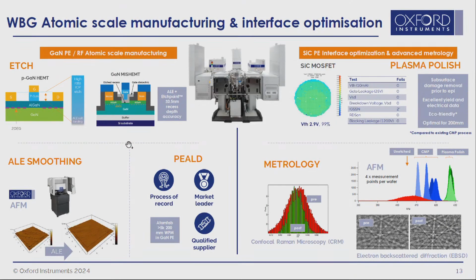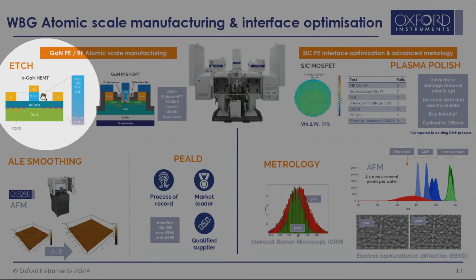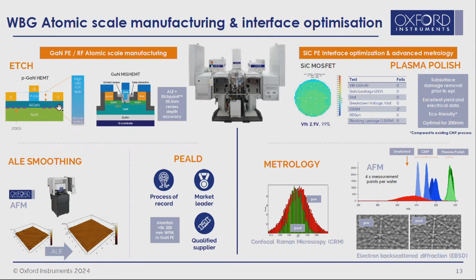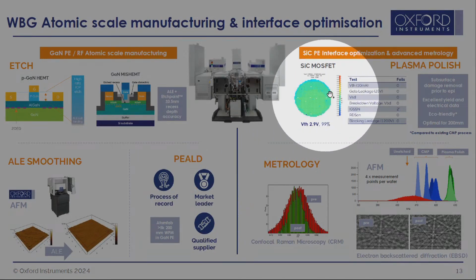So this is for an RF type GaN device, or alternatively also smoothing in a p-GaN HEMT. On the right is a process that we have for silicon carbide, and that is an alternative to using CMP, etching the surface with a plasma to effectively polish the surface in a similar way to CMP, but removing the surface damage.